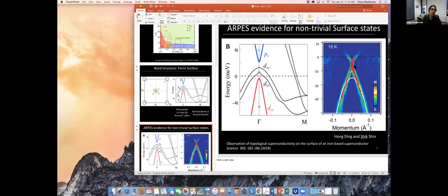You want to do this as a function of doping, I presume? No, just 50-50. And if I may comment, this was just done. I posted the link to the arXiv paper. So there is an appearance of the topological surface state as a function of tellurium concentration and disappearance of superconductivity. No, but I'm asking about a bulk, not a surface state. Yeah, there is appearance of a surface state which is indicative of a band inversion in the bulk. And that's as a function of tellurium, and actually happens not at 50%, but around 55. Yeah.